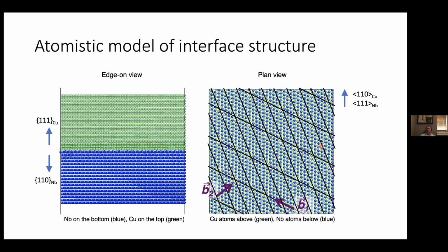Now, an important fact about this particular interface is that both sets of dislocations in this interface have Burgers vectors, indicated here by these arrows, that are entirely contained within the interface plane. So these Burgers vectors are completely within the interface plane. They have no component pointing out of the interface plane. Those of you who are familiar with dislocation mechanics recognize that when you have a dislocation with a certain direction and a certain Burgers vector, the plane that is defined by those two vectors is the glide plane of the dislocation. So the glide plane of the dislocation, the plane along which the dislocation can easily move, is the plane that contains the line direction and the Burgers vector. So in the case of these particular sets of dislocations, the glide plane of both sets of dislocations is the interface plane, and that's a fairly